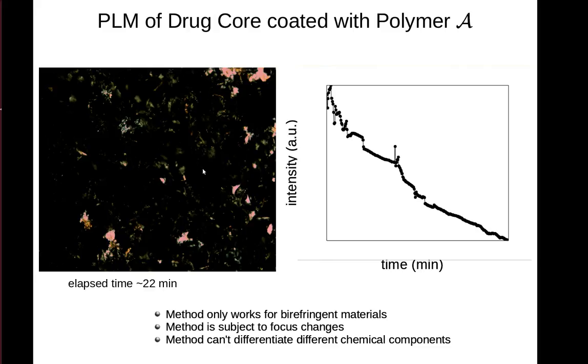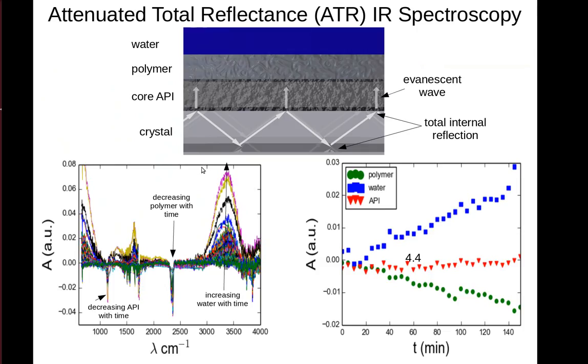A very similar measurement that we can do, but get more of this chemical information, we will use spectroscopy. Specifically, we will use Attenuated Total Reflectance, ATR, infrared spectroscopy. In this measurement technique, there is a crystal in which the IR radiation is passed through. It is totally internally reflected, and each reflection point produces an evanescent wave that penetrates above the crystal surface, in this case into our core and polymer material. The experiment here is called a triple bounce. The radiation is actually bounced 3 times off the crystal surface before being recorded.